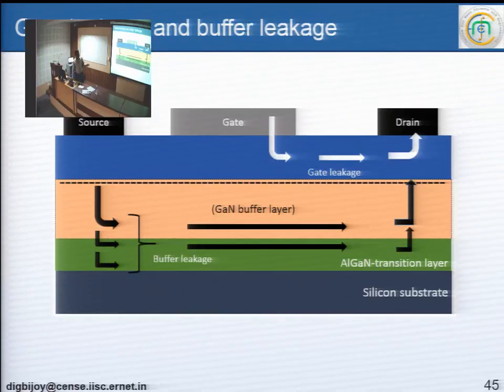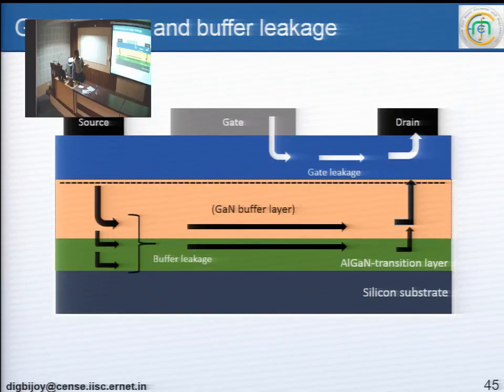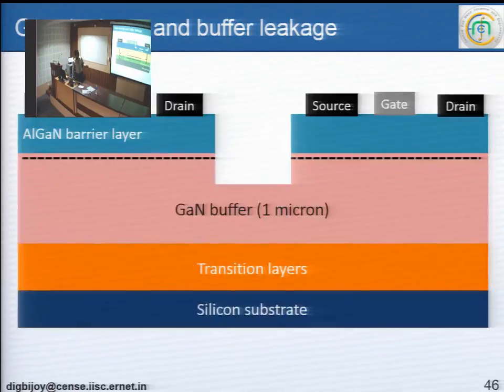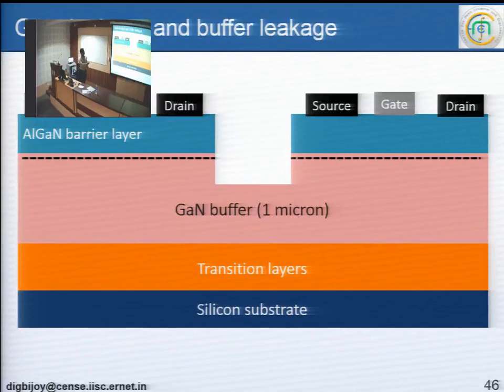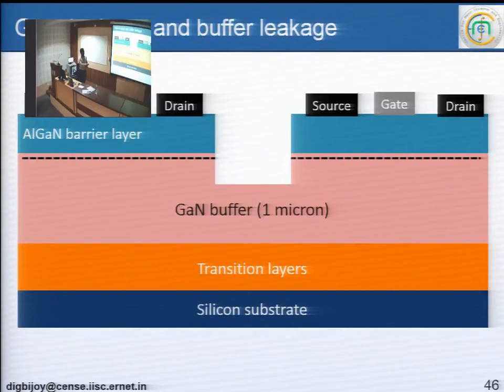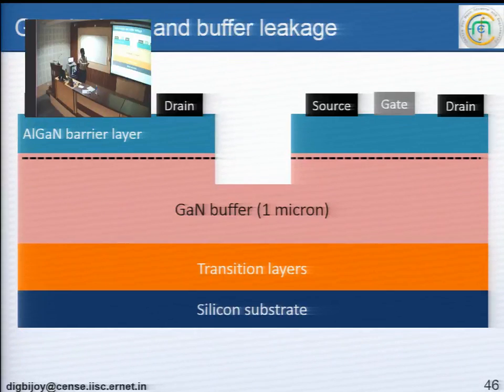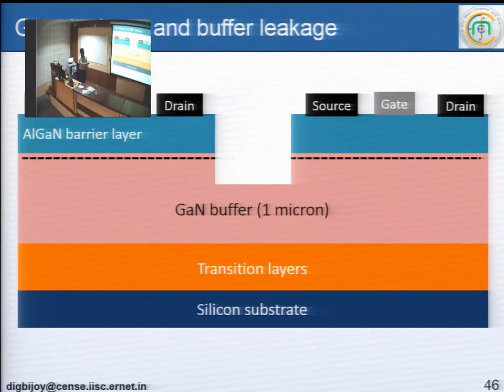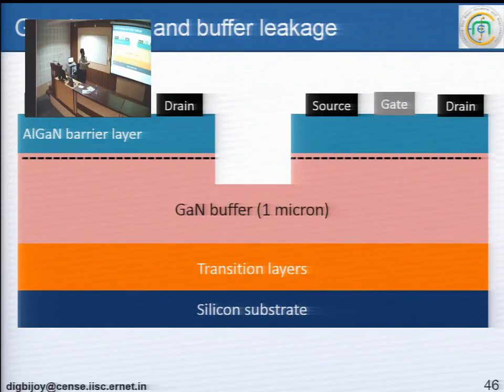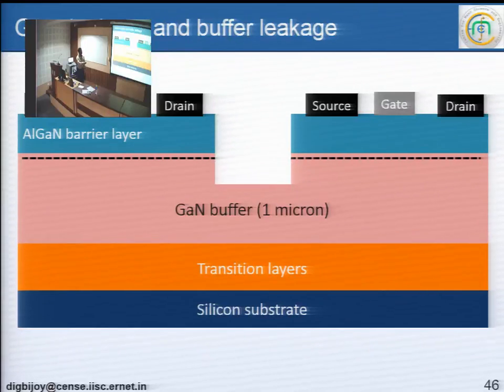So how to measure gate leakage is very easy. You put one probe here, you put one probe there, and you just measure what is the leakage, which should be very low. How do you measure this buffer leakage? Say you take two transistor structures and you etch away or remove the region between them. If you remove the 2D electron gas, the electron channel between them, you measure between this terminal and this terminal. There is no path, right, except for this. So if you see a very high current, it means that you are going through this route, which is not wanted. It means your transistor wafer is bad. If you have very low leakage, it means you have a good transistor.